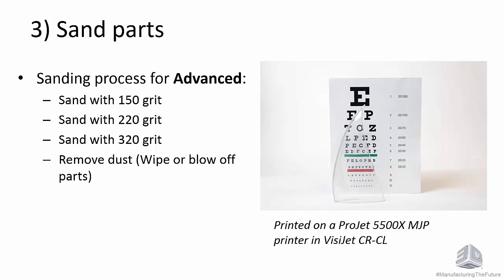For advanced, it's actually less sanding, and the reason why is the clear coat that you spray with the automotive paint is thinner, it's more running, and so it will go through and fill in all those little cracks and crevices. So there's no point in sanding more than that because those sanding lines are all going to get filled in with the paint. And so you start with 150, then you go to 220, then you go to 320, again removing the sanding lines from the previous grade. And again, before painting, you want to remove dust.